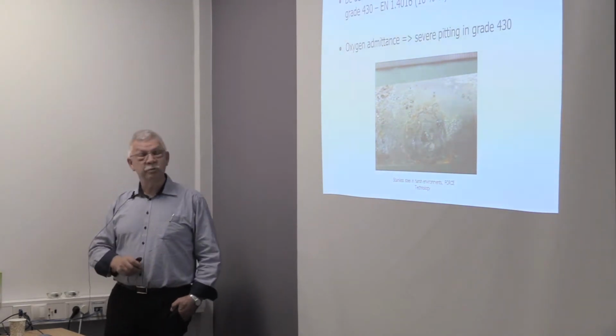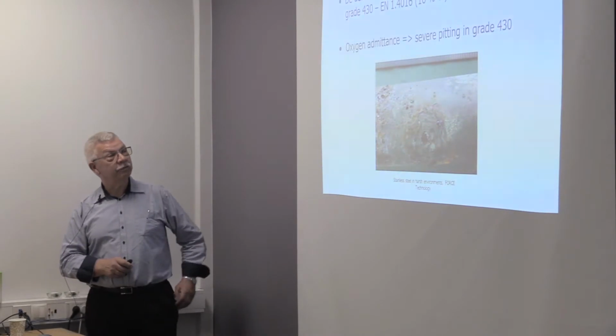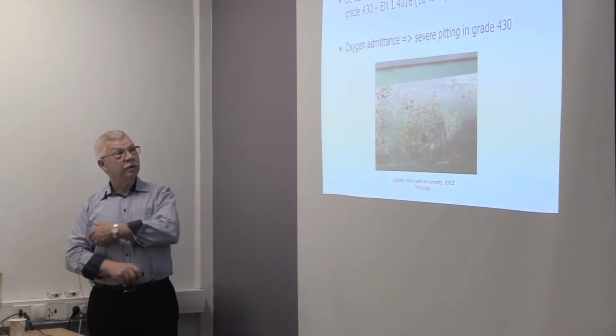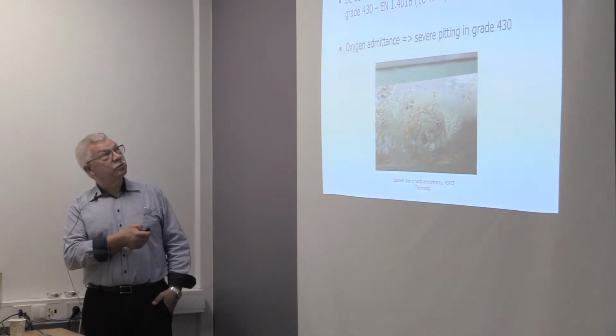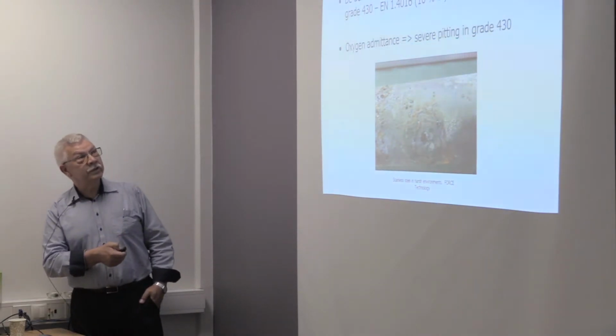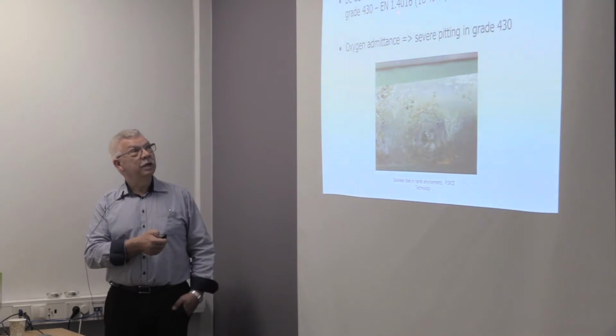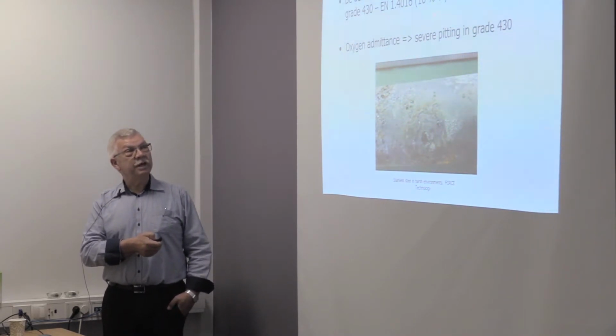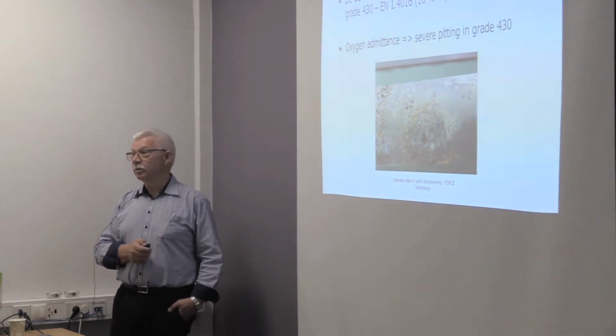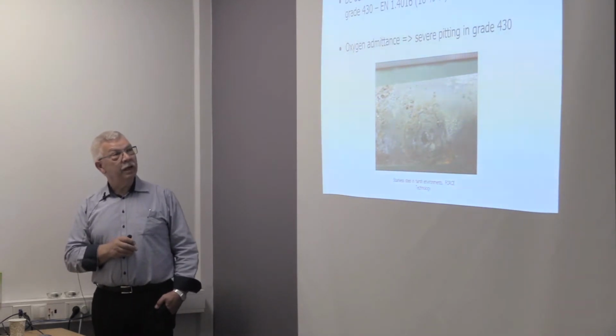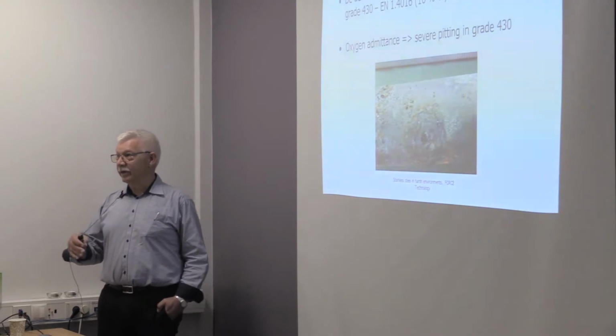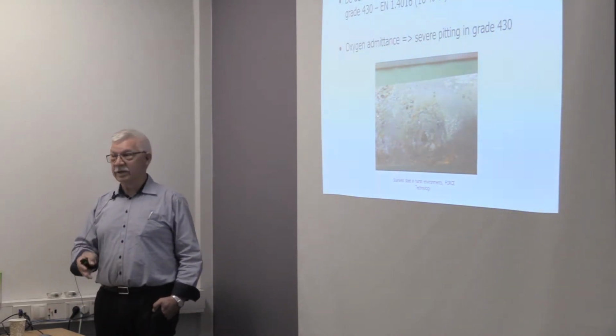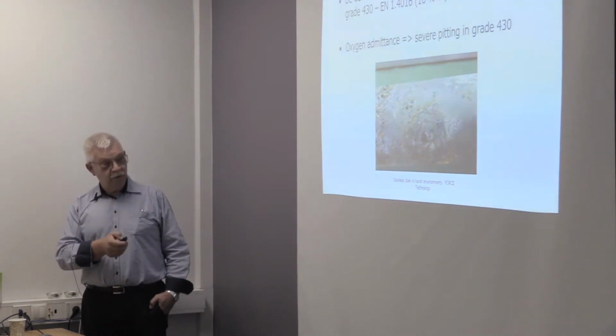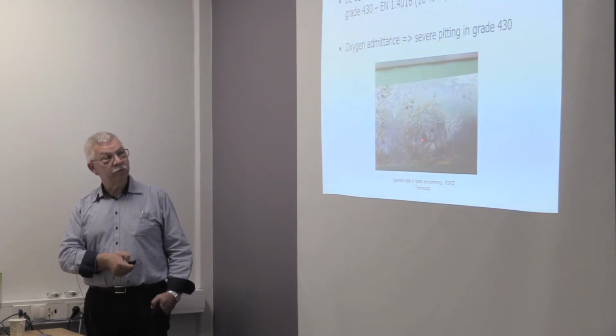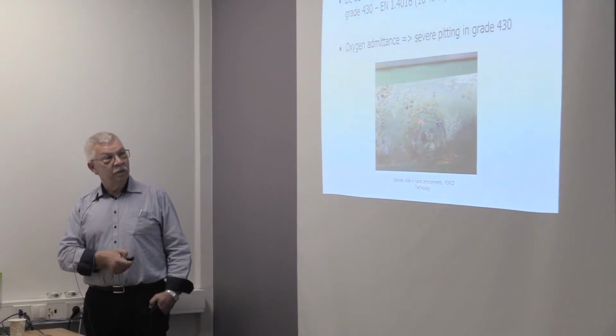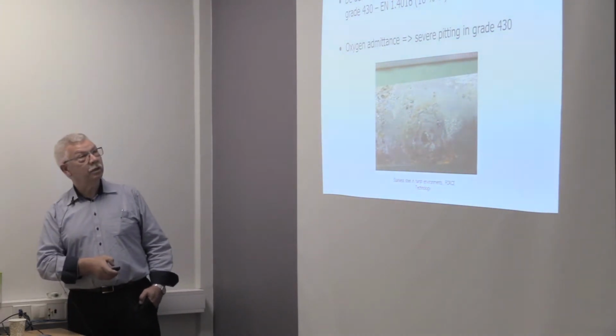I have one example though, which is related to geothermal conditions. It's from a heat exchanger on a heat pump, and as the conditions were to be without oxygen, ferritic stainless steel, the grade 430, which is 16% chromium steel, would be safe, but only if there was no oxygen. And in this particular system, they had some problems during the commissioning when they were starting up. So it was left standing still. Oxygen entered the system, and the result within a year was that this heat exchanger could be cut out. There was pitting corrosion everywhere in these tubes.